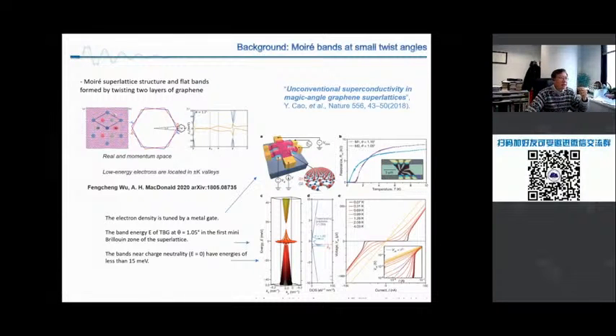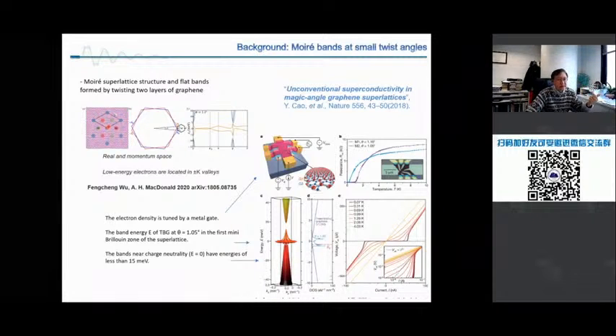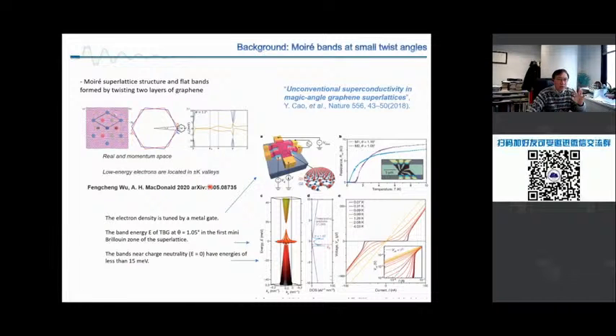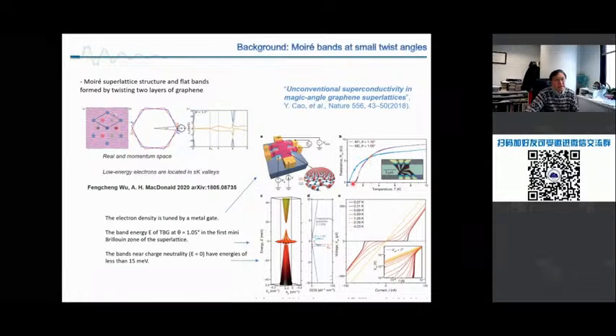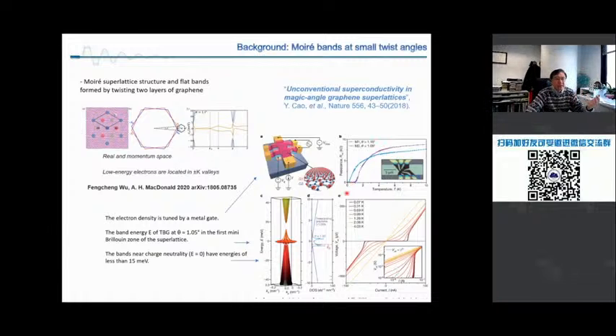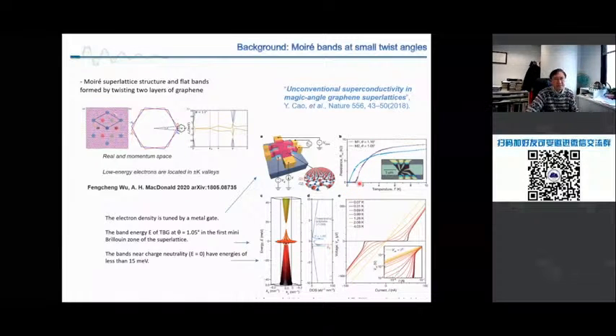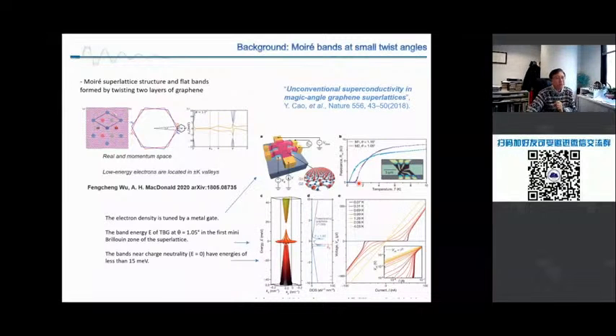So what do you mean by filling? You count how many electrons you fill per unit cell. That's what filling means. For graphene, there are 4. You need 4 electrons to fill per unit cell, and you get 4 filling. So at certain fillings, you see very nice curves of superconductivity. That means you measure resistance is 0. At a certain so-called magic angle. Magic angle means when you calculate the band structures at a magic angle, it's ideally flat bands.